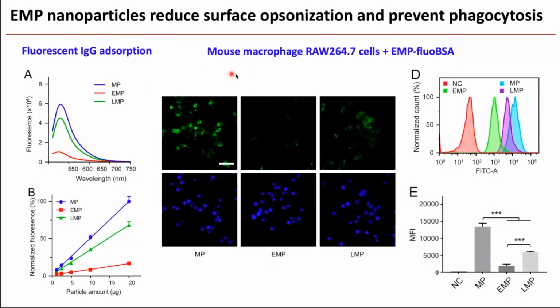We further studied this using a mouse macrophage line, and in this case, we show that after the nanoparticle is coated with this EV membrane, the uptake by macrophage is significantly reduced compared with the particle without coating and also with liposome coating.